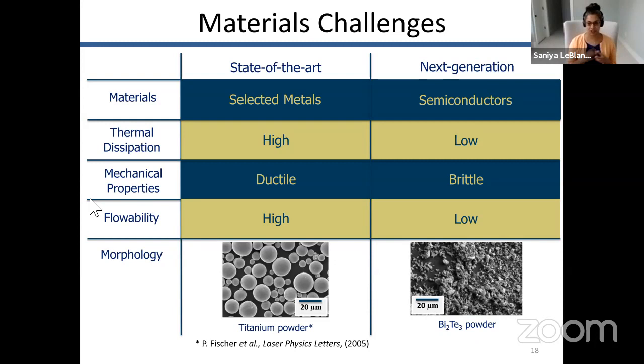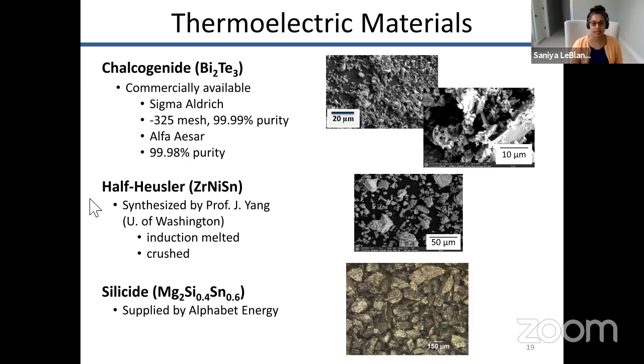So we've worked with different thermoelectric materials to do this additive manufacturing technique. We've worked with the traditional chalcogenide, which is bismuth telluride, that is used in the commercial thermoelectric modules that you might buy off the shelf. We've worked with Heusler materials and silicide materials as well. And what you see on the right there are some images of what these powders look like. So they're not typical powders.